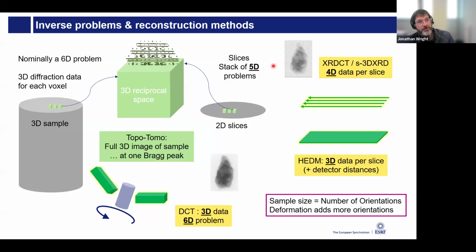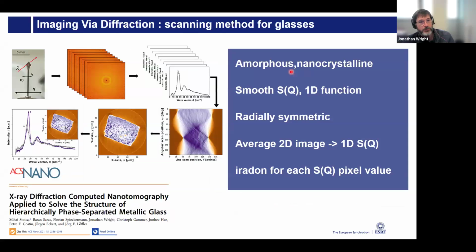So at this point, we're only missing one dimension. So we're, should we say, almost respectable. We can get back in the case where the sample has some symmetry and be fully respectable. So in this case of glassy samples, this works fantastically well. So this is a bulk metallic glass that Mihai Stoica and co-workers brought to the beamline. And in this case, it's a metallic glass that segregates like oil and water, so something like a salad dressing. And you could resolve the different components inside the glass by looking at the X-ray diffraction data.